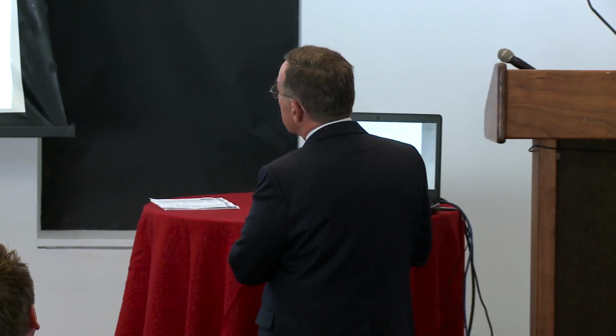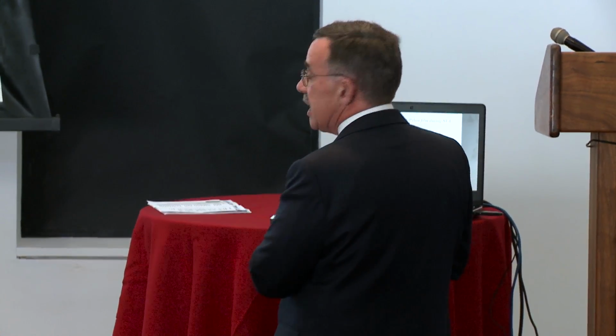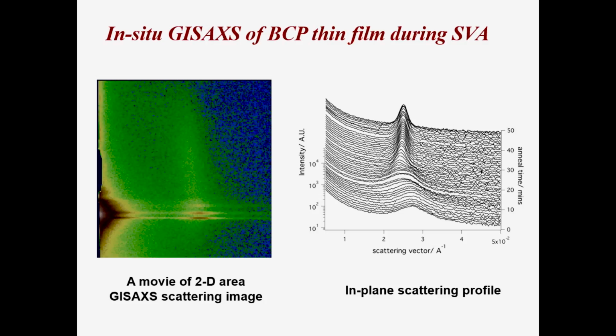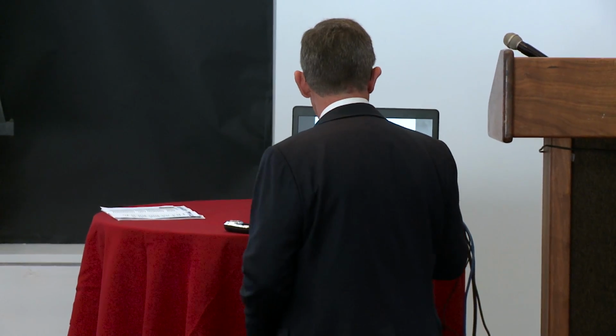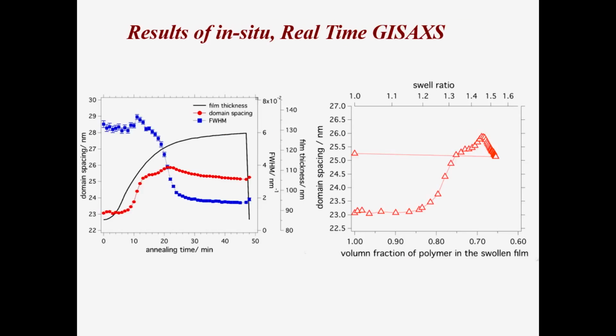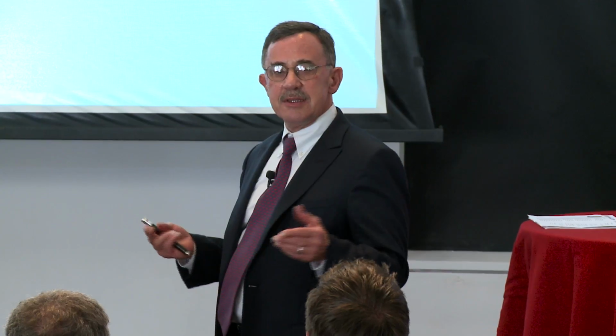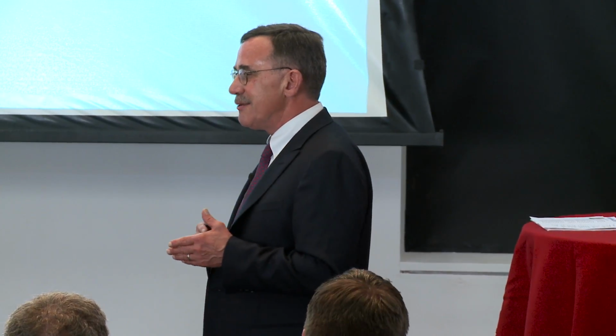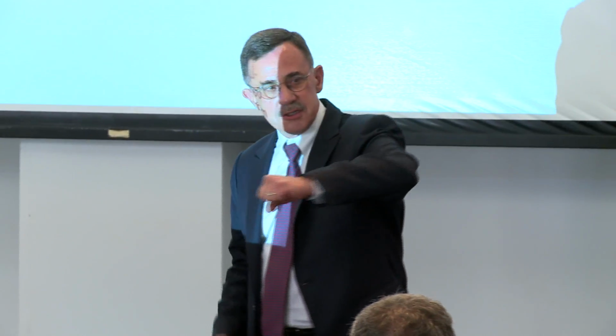And so what happens is that these copolymers begin to phase separate. The phase separation improves when you introduce a solvent because I've given the system mobility. And in fact, you can now monitor the position of the reflection, and this is characteristic of the domain size. And that's given by the red. We start off initially with the spin-coated film, a non-equilibrium structure, introduce solvent, the spacing gets bigger, and then something curious happens. The spacing starts to decrease. And the reason the spacing starts to decrease is that the system initially stretches, and then we continually add solvent